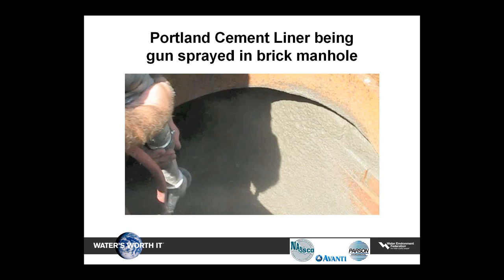Portland cement-based products will usually exhibit the longest working times. This type of product can typically be applied at a thicker rate per coat than calcium aluminate-based products. The 28-day compressive strengths are typically a bit higher than the calcium aluminate materials, which gain strength much earlier in the cycle and then tend to move upward more slowly.